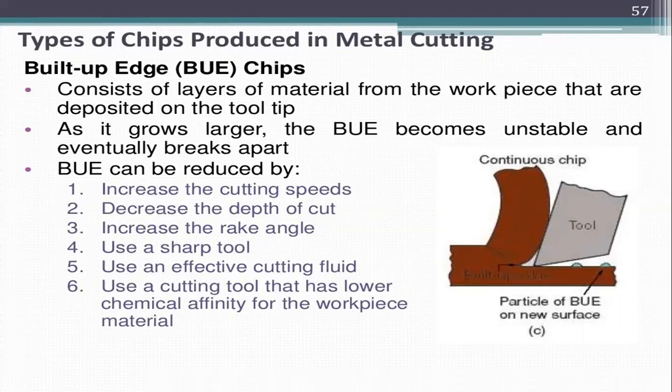This can be reduced by increasing the cutting speed, decreasing the depth of cut, increasing the rake angle, or we can use a sharp tool, or an effective cutting fluid, or a cutting tool that has a lower chemical affinity for the workpiece material.